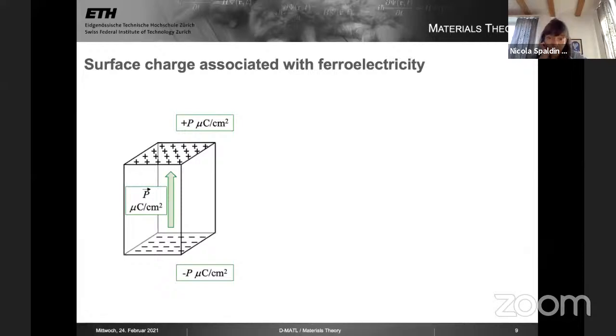But there's a problem when one starts working with ferroelectrics in thin films, and that's that when one has a polarization, then there's a charge associated with the surface perpendicular to that polarization. And one can see that rather intuitively if you think about just the units of polarization. It's dipole per unit volume, which is charge per unit area. Usually it's reported in microcoulombs per square centimeter. And so if there's a polarization of 50 microcoulombs per square centimeter, that means at one end of the thin film, there's a charge on the surface of the same magnitude as the polarization. And of course, it's negative on the bottom end and positive on the top end of the polarization.